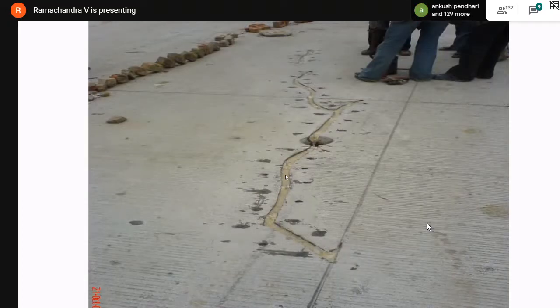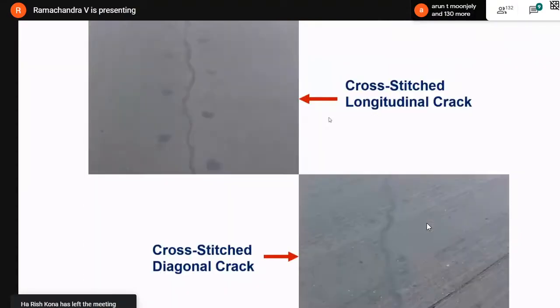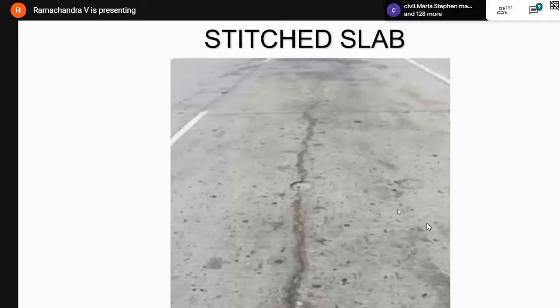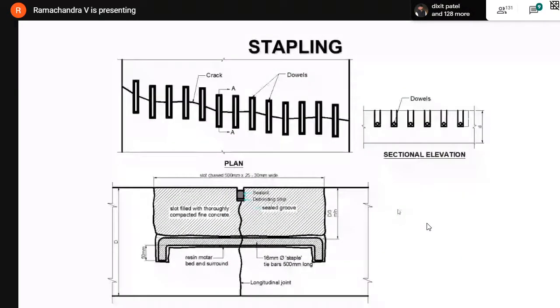You can see that once that is done, on either side it is filled, and this is a finished surface. Now this is how it looks after the cross stitching of the longitudinal crack is done. This is a diagonal crack that is cross stitched. This is a stitched slab. Now performance is perfect. The only thing is that you may see that mark there, a color difference there, that is okay. But then the pavement performance is restored. Now another way of doing it is stapling.